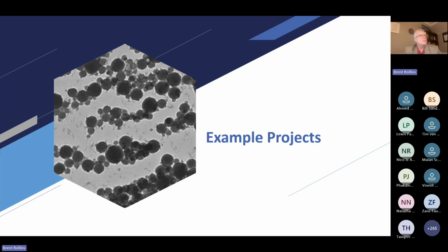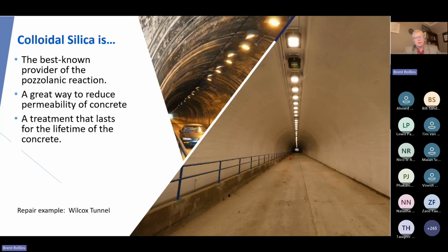I've got a couple minutes. I want to share a couple of quick example projects. Colloidal silica can be used on new concrete, or it can be used to treat existing concrete. If you treat existing concrete with it, the main thing to remember is that the material must be able to get into the concrete to be effective. And sometimes that requires mechanical opening of the concrete surface with things like grinding or shot blasting.